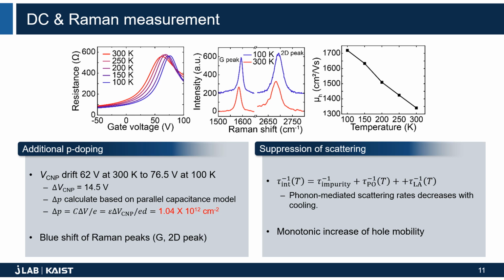Also, the increased hole doping of graphene is observed by the blue shift of the G and 2D Raman peaks. In addition to the change of doping concentration, the cooling also reduces the carrier scattering in graphene. In our measurement, there appears a monotonic increase of mobility with decreasing temperature.